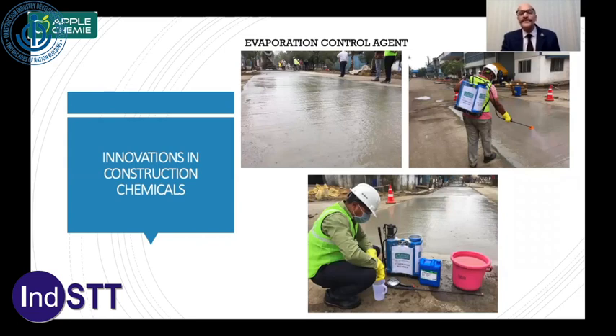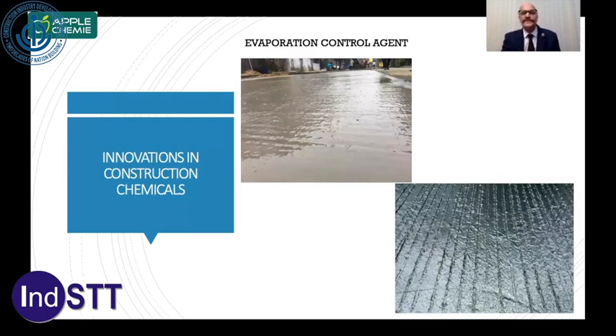Well, talking about the evaporation control, there is recently a new development. A product has come which is an evaporation control agent. Now, this evaporation control agent is a liquid which you can spray immediately after the casting is done on the pavement. So the evaporation control takes place, and thereafter you can put curing compound. Well, this is what I have shown in the picture: in the first slide you can see the evaporation control agent put, and thereafter, after half an hour or so, when the concrete can retain its texture, you can do the brooming, texturing, and curing compound.